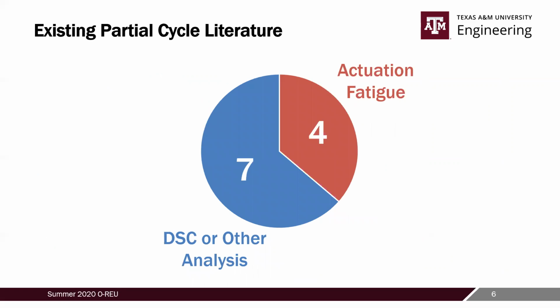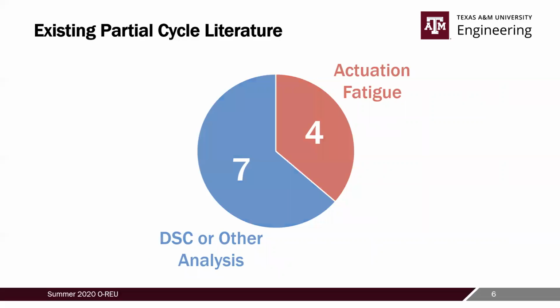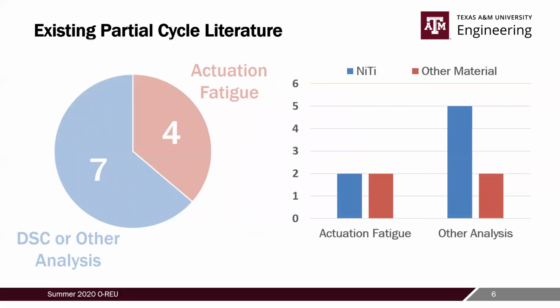There isn't much literature out there on partial cycling of shape memory alloys, but from the 11 papers I found in my literature review, there were 4 of them that included actuation fatigue studies like the ones that we're doing. The other ones all mostly focused on differential scanning calorimetry or some other type of analysis. And of all those papers I looked through, most also focused on nickel titanium, even though there were a few that analyzed other materials like nickel titanium copper.